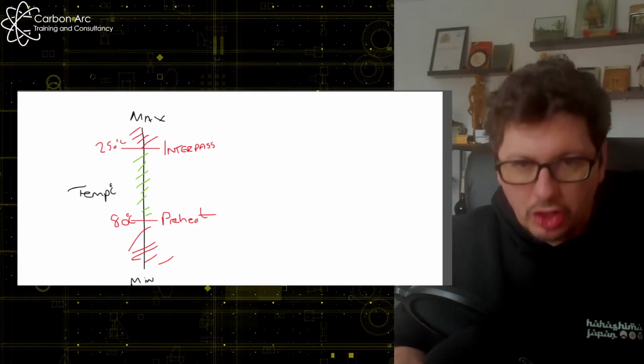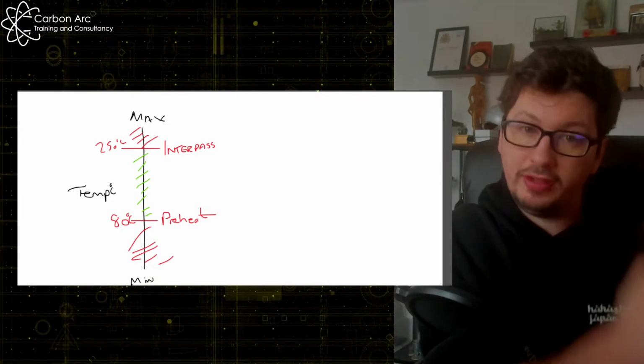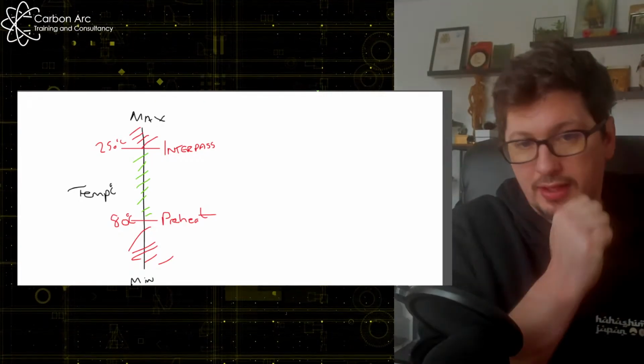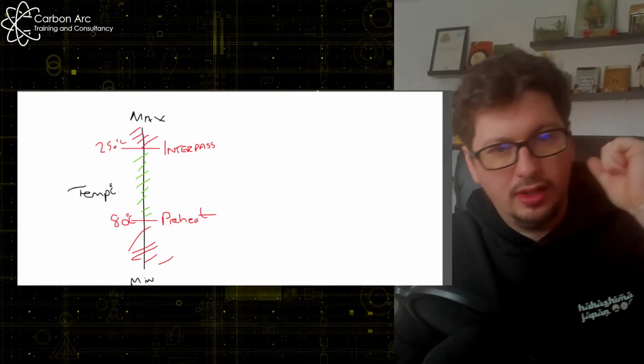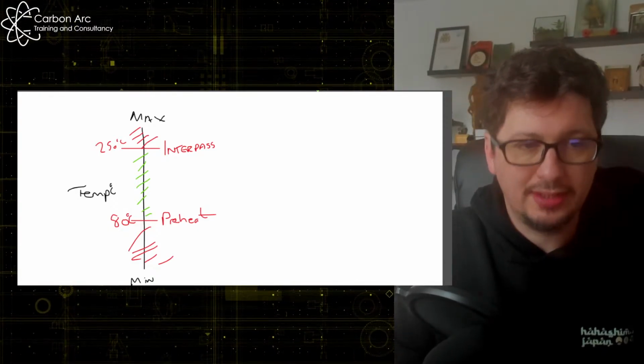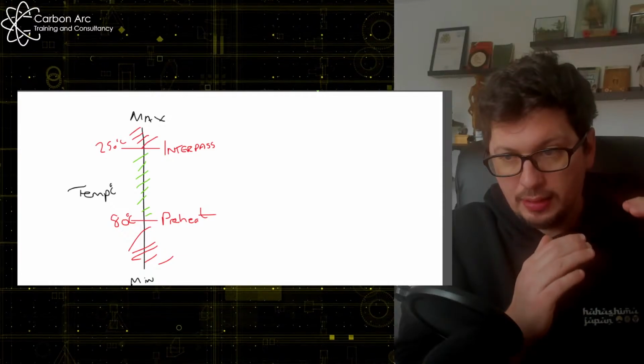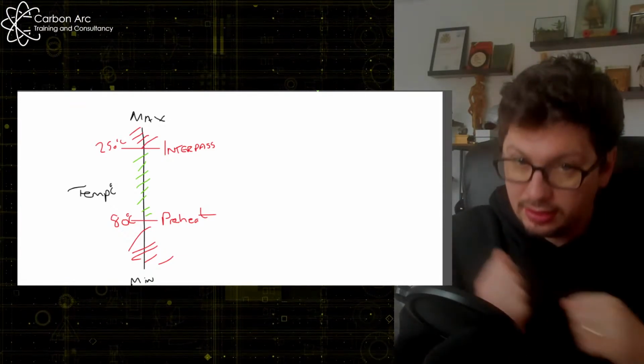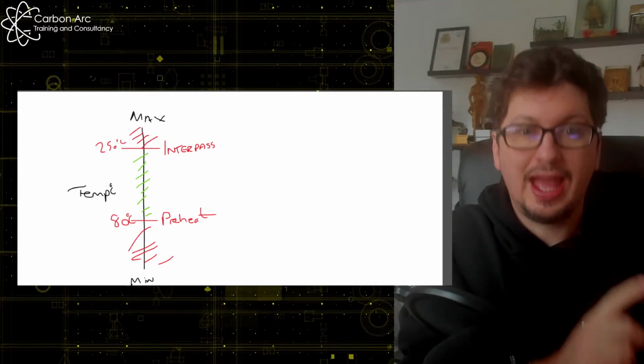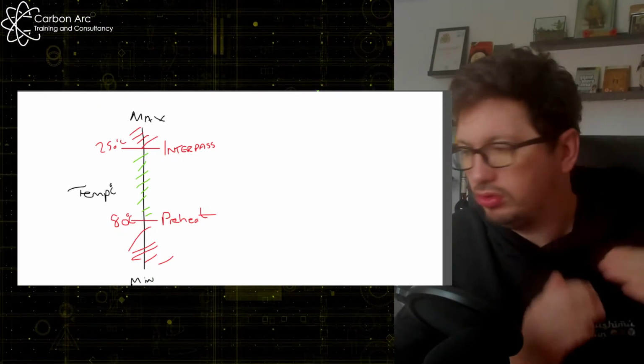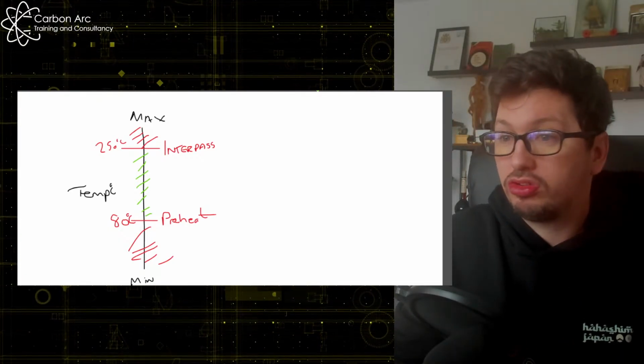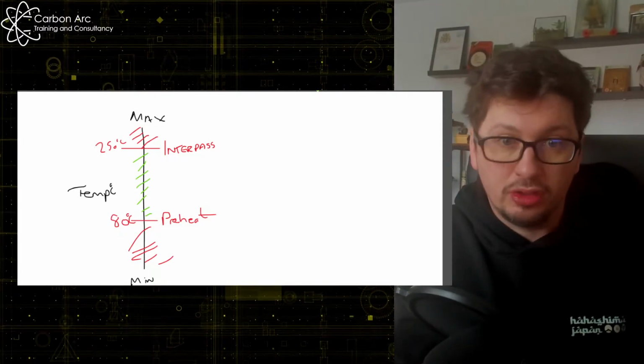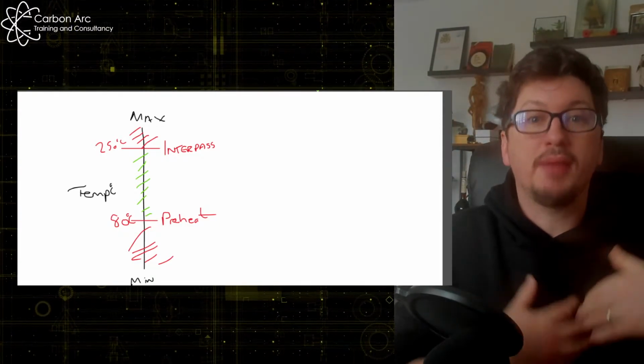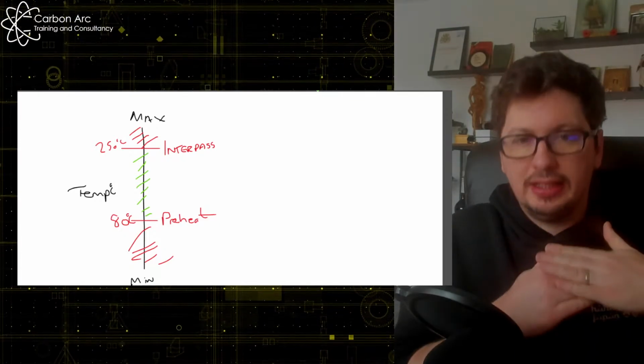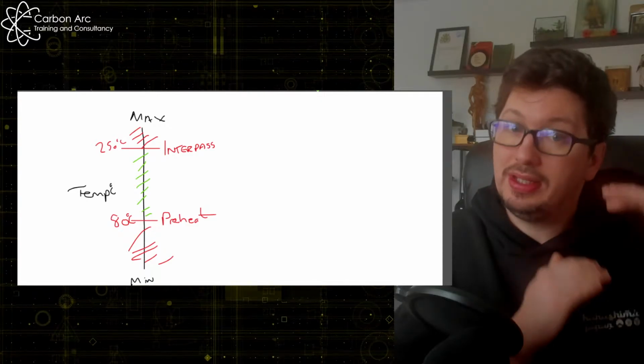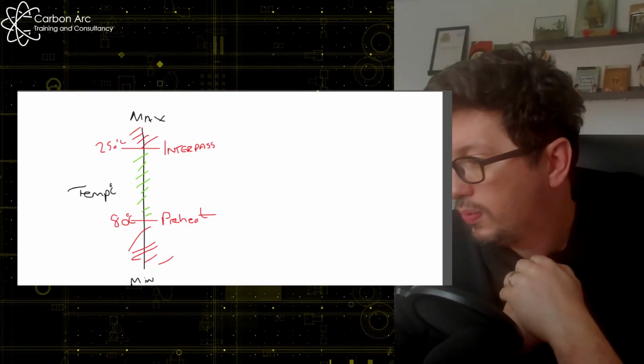So that means I've now got my upper limit and my lower limit within which I'm allowed to weld. When I start the day, I have to preheat it above 80 degrees. And when I'm welding, if I finish a weld run and put my probe on it and it reads 400 degrees, I've got to stop, let it come back down, and once it's under 250, I can start welding again. So that's your preheat and your interpass temperature between runs. Now, if I stop for my lunch break or for the afternoon and go home, and come back the next day, of course, I'm starting welding again, so I'm back to my preheat to heat it back up and then stay between those lines. Hopefully that made sense.